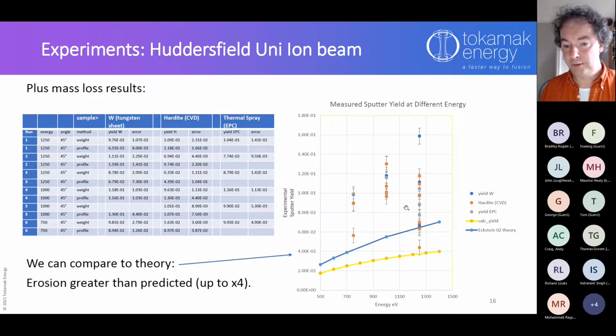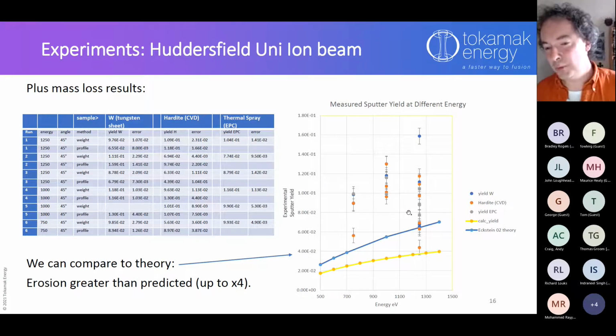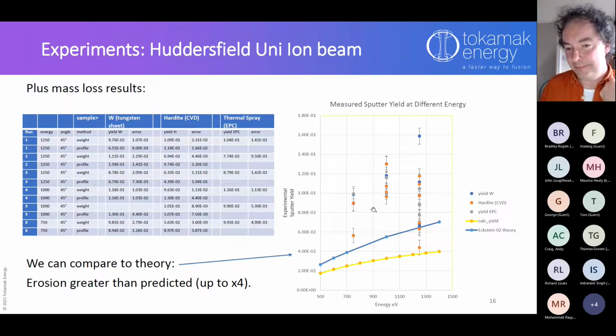So you see we've done quite a lot. I honestly think that these error bars are too small because you can see there's a pretty big spread here. But this sort of initial experiment showed us that it does kind of follow the trend. Maybe you might need to squint your eyes a bit, but it does seem to be going up, and so it's not a million miles away. It's the right order of magnitude in terms of sputter yield, but in general they are higher than we've predicted, up to about 4 times.